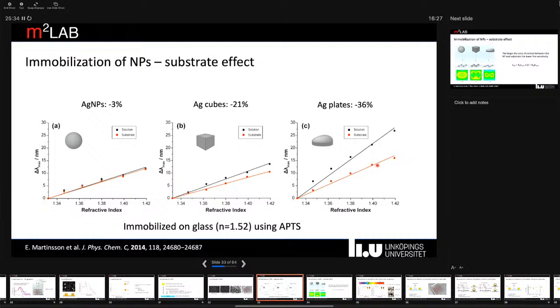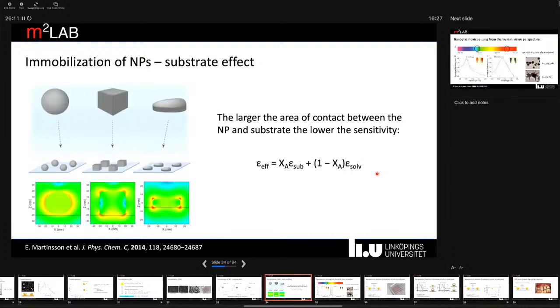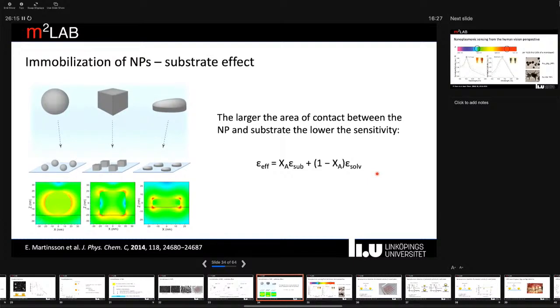As we can see in this data, here we have spherical silver nanoparticles, and if we immobilize them on a glass substrate, there is essentially not much of a difference in sensitivity, whereas if we go for cubes or plates, also silver-based, we see a quite dramatic decrease in sensitivity. These particles were originally more sensitive than the spheres, but due to this effect, this difference is decreasing quite a lot. This is due to the high refractive index of the substrate, resulting in some of the electric fields being distributed into the material instead of probing the surrounding medium. And the larger the contact area between the particle and the substrate, the larger this substrate effect. So we should try to keep this at a minimum, or, if this is critical, use low refractive index substrates.